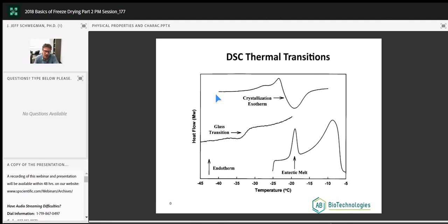So here, for example, let's look at a standard eutectic melt. We warm, see this nice sharp peak, symmetrical in shape. Classic example of a eutectic melt. Anytime we have a eutectic melt, you're going to see a nice sharp peak. You'll never miss this. It's a high energy event. Let's contrast that with a glass. Now the glass, as we warm up, goes through this characteristic, what we call the S-curve. So just by the shape of these curves, I know what it is.